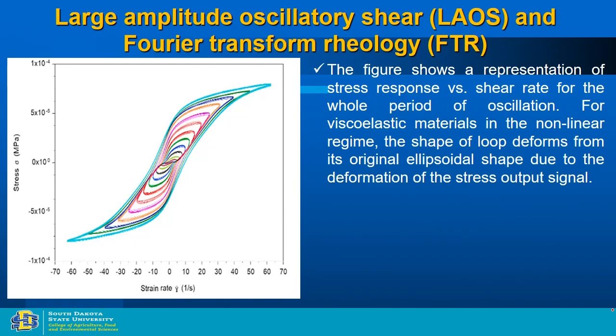Let's look at the large amplitude oscillatory shear and Fourier transform rheology. What you see here is the stress as a function of shear rate. It's a stress response for the shear rate you apply for the whole period of oscillations. You start in the middle of the oscillations, and for a viscoelastic material in the nonlinear regime, the shape of the loop deforms from its original ellipsoidal shape due to the deformation of the stress output signal. So this is what you get in large amplitude oscillatory shear for any food material. This is a typical output you get when you do the non-linear rheological analysis compared to the linear viscoelastic region.